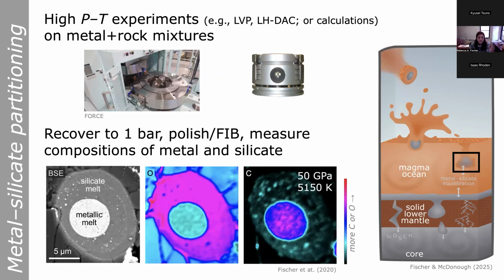So we can investigate the partitioning of elements between metal and silicate using high pressure temperature experiments. This has been done quite a lot in large volume presses, like the ones at Force. In my group, we do this using a laser heated diamond anvil cell to get to high pressures and temperatures. And other people are starting to do this using ab initio or other computational methods. Basically, you take a mixture of metal and silicate, bring it up to some high pressure and temperature, melt it, let them react for a minute, and then quench it to sort of freeze in that chemistry.